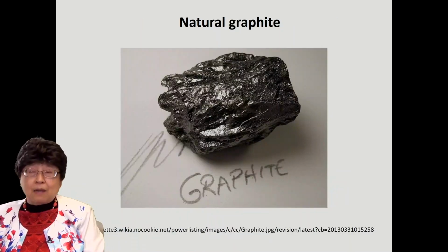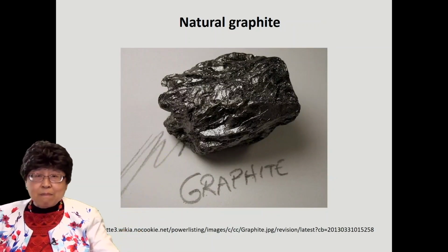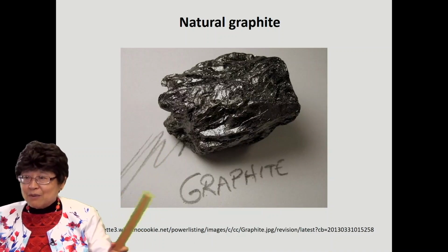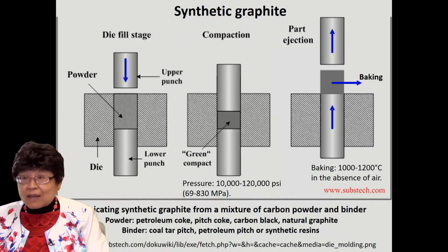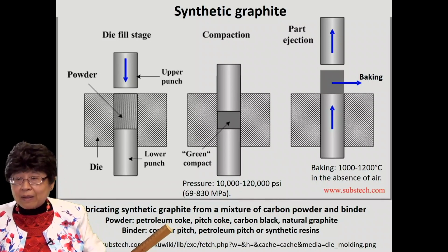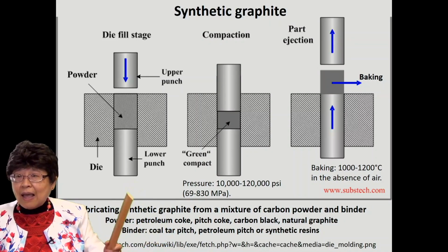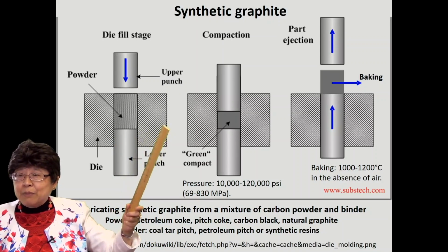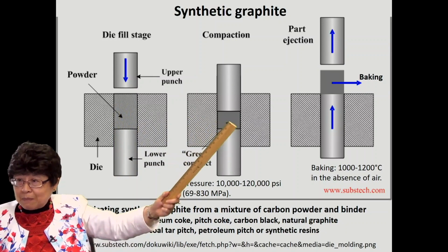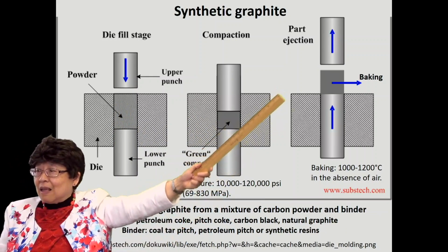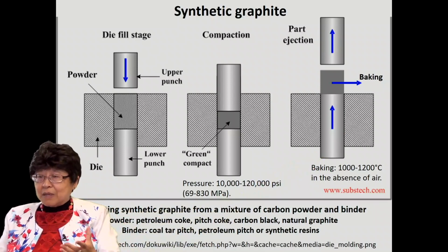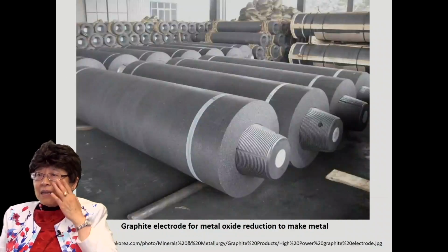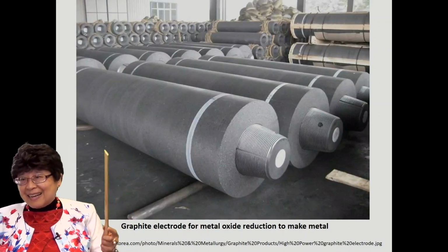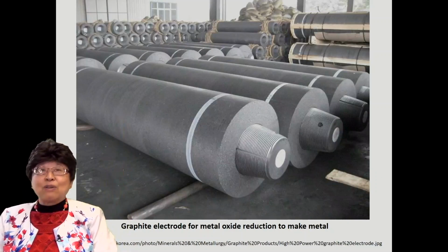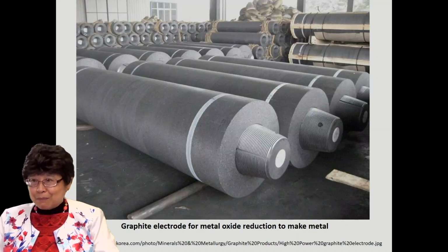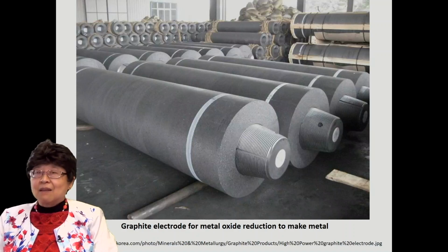Now, there are many types of graphite. Natural graphite you can mine from the ground. Okay? It's a mineral, and you can write with it like a pencil. You can also make synthetic graphite by taking some coke particles and some pitch as a binder, and mixing the two together, putting it into a die, which is a mold, compacting that under high pressure, and then heating that to high temperatures, and it becomes a chunk, and that's synthetic graphite. Okay. And this chunk can be very big. This big size is actually a graphite electrode that's used for metal oxide reduction to make metal. It's a big industry requiring such big graphite electrodes.